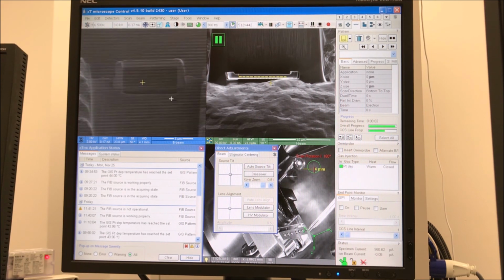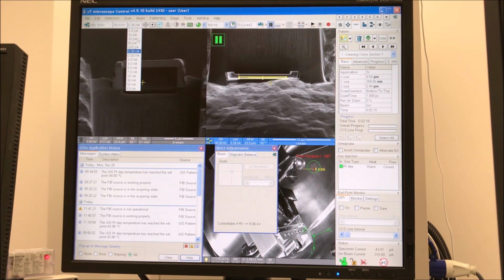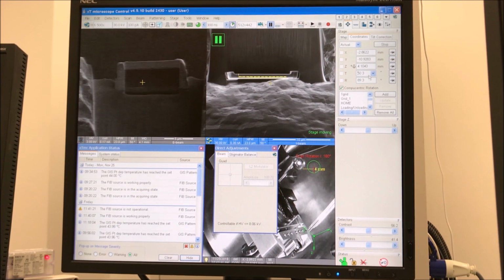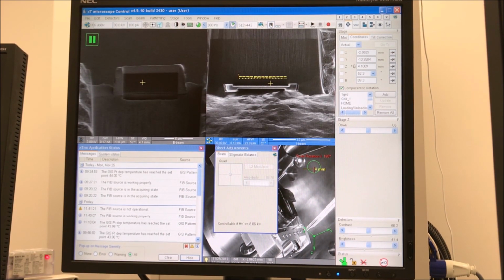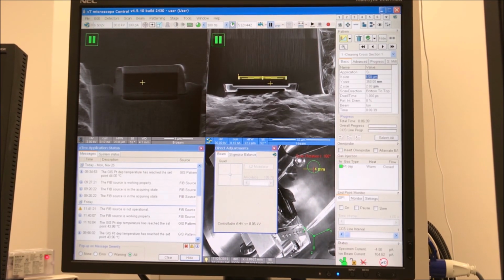And so once this pattern is done, I'm going to drop the current down again to now 100 picoamps, tilt 1 degree away from normal incidence, plus 1 degree I should say, reduce the X dimension again, rotate 180, and now I'm going from the top side of the lamella.